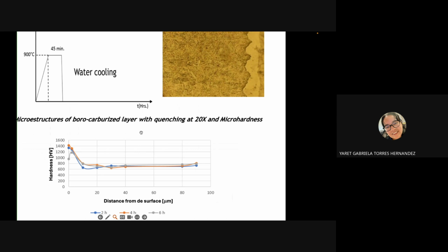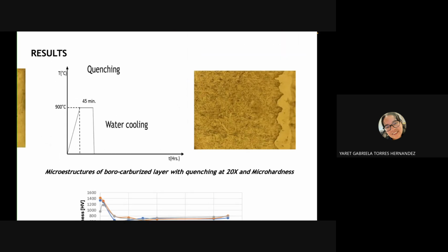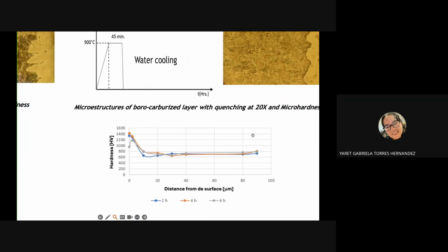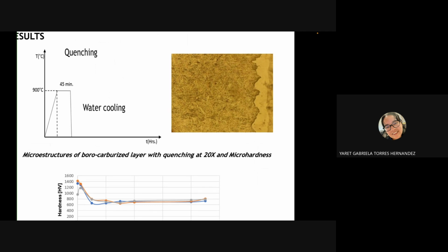Finally, the quenching treatment was applied for 45 minutes with water cooling. In this case, the microstructure presents martensite in the layer and a hardness of 700 HV of the borocarburized layer. The morphology of the layer was flat and the depth decreased by approximately 40%.